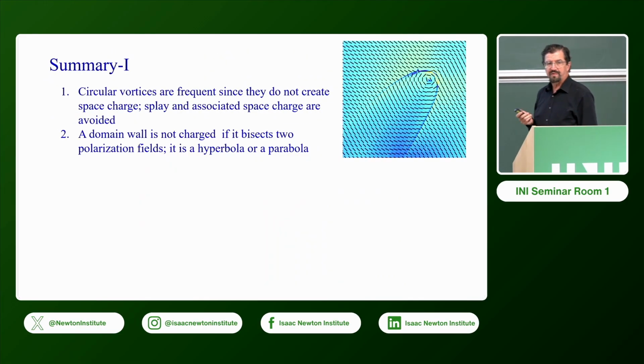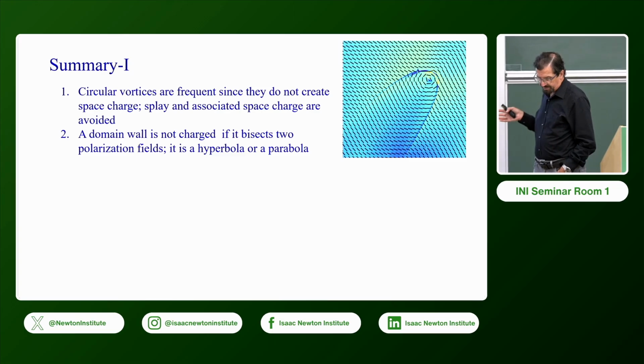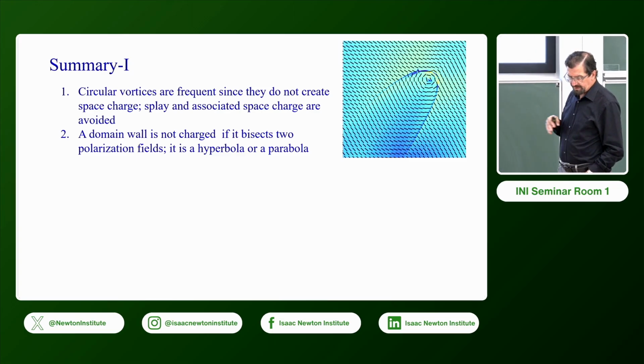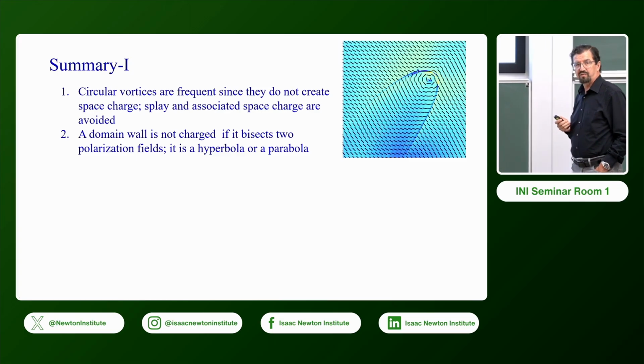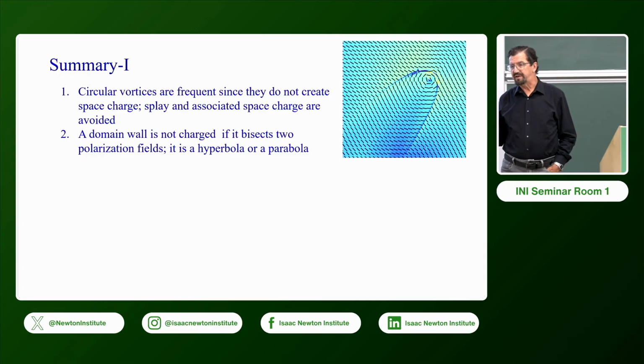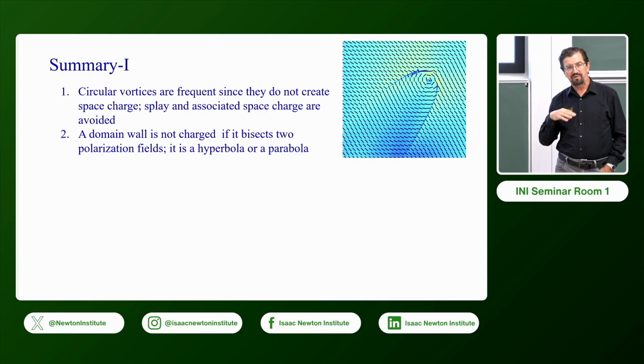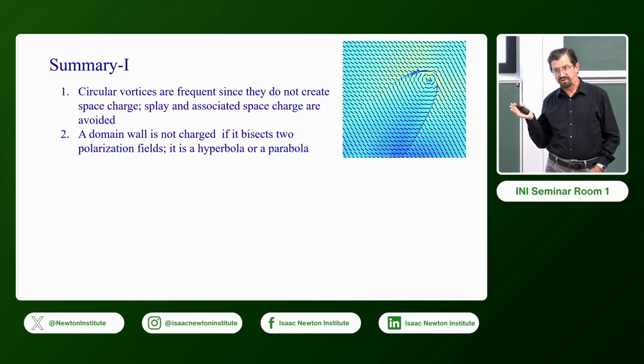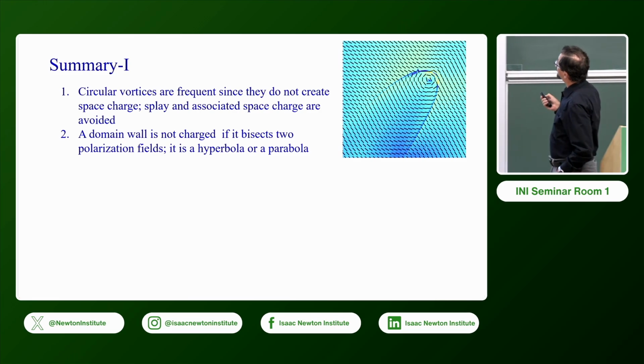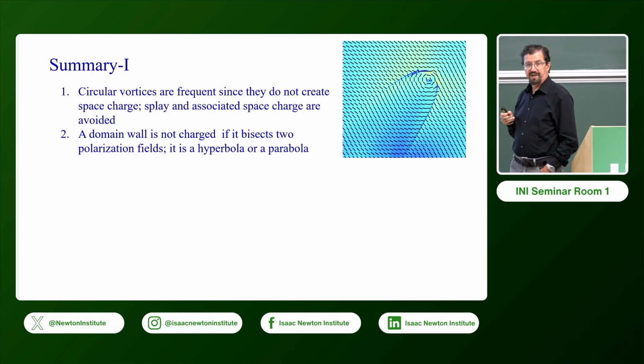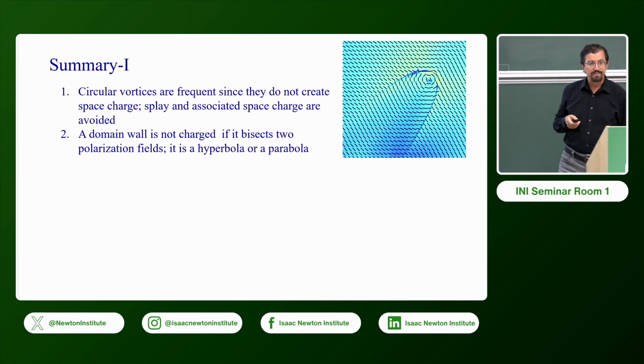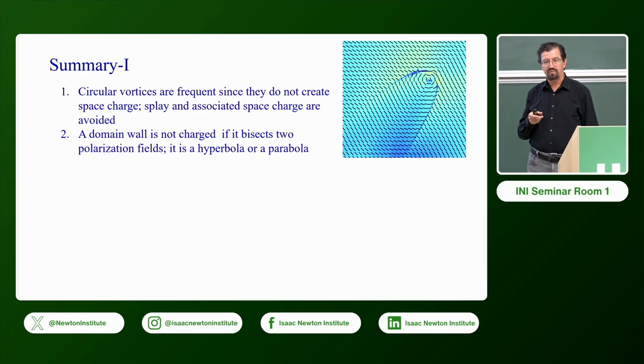So to conclude the first part, if there are no externally imposed limitations on the orientation of polarization, the ferroelectric nematic would try to avoid surface charges and charges in the bulk by producing a lot of circular domains and conic sections as the means to separate them.